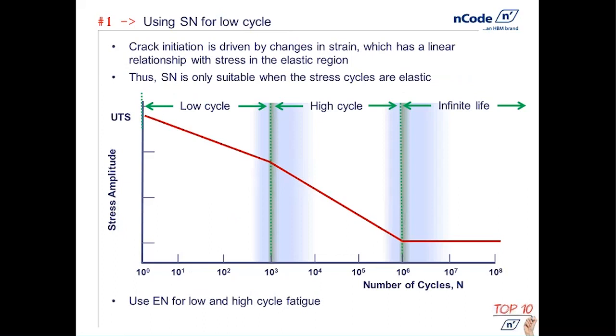What we know from a more detailed look into the way in which cracks initiate is that it is something that's driven by changes in strain. Now we know that stress and strain have this nice linear relationship so long as we're within the elastic region, and that is where the stress-life approach works really, really well. This region is something that we would also call the high cycle region.